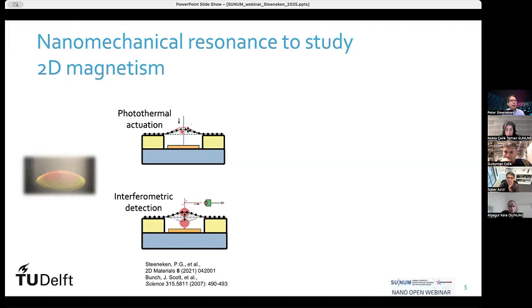But then the second question is, how can we actually measure and know if it's really resonating? For that, we use a second laser, a red laser. There's the substrate below the membrane, which acts as a mirror. If this red laser reflects from that mirror, it creates a standing wave pattern with nodes and antinodes. When the membrane is moving through this standing wave pattern, it absorbs less or more power and attenuates the reflected light by its movement. If it's in a region where there's a high red laser intensity, then it absorbs more and you get a low intensity on your detector. Whereas if it's in the middle, it absorbs less energy and you get a higher intensity on your detector.